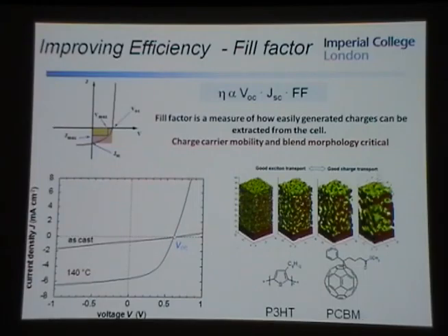performance of the device. So that's quite a frustrating thing in terms of making new materials, because it's quite hard to control what type of phase segregation you get. And really the only tools that we have to do this are trial and error approaches. So we make the blend, we anneal it at different temperatures, and see the effect on the performance. We maybe use different solvents or different processing additives that have selective solubility for one of the two components, so that can control the crystallization as you come out of solution. But it's not particularly well understood, and it is a trial and error approach.